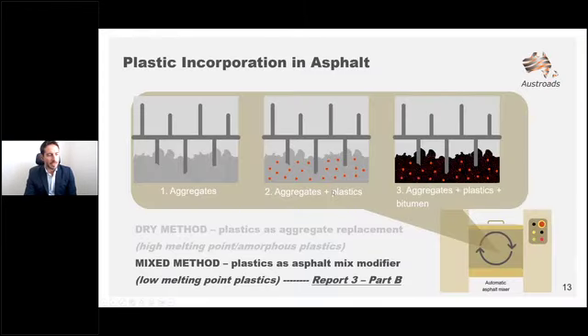In the previous webinars, we presented the wet method, so bitumen modification, and the dry method, where we were using plastics as an aggregate replacement. In today's presentation, the mix method is actually a combination of both. The plastic is added directly to the pug mill, or to the hot aggregates, in order to create a polymer modification, a polymerized coating of the aggregates, before the bitumen is actually added afterwards. So we need to look for plastics that are capable of melting around that mixing temperature of 160, 170 degrees Celsius. So we're looking at low melting point plastics.